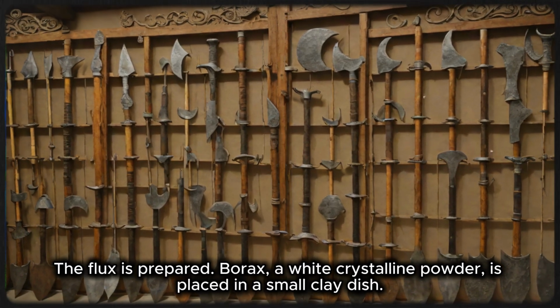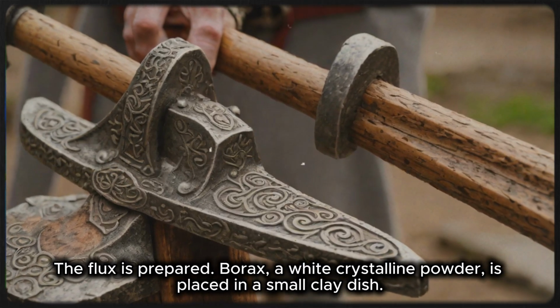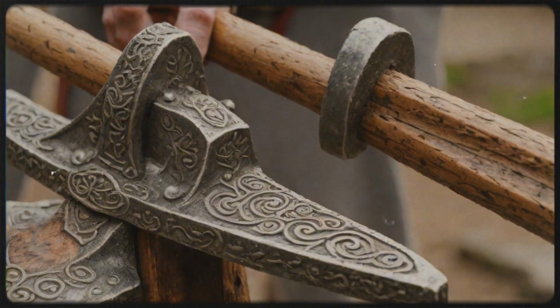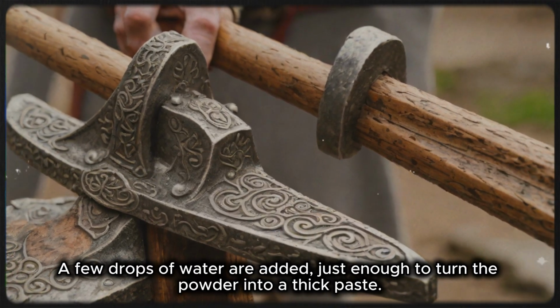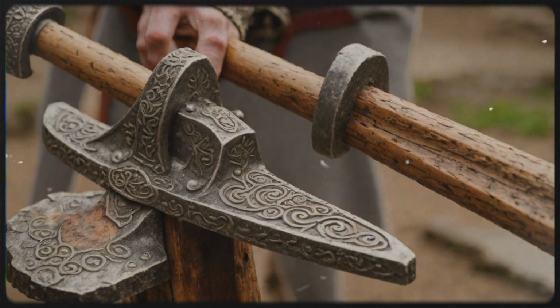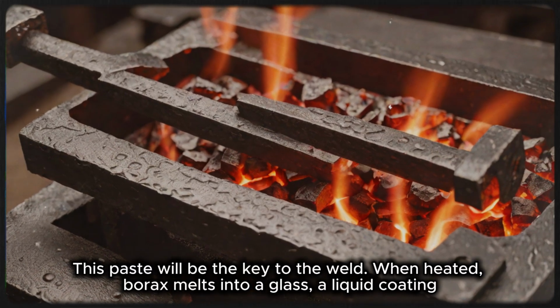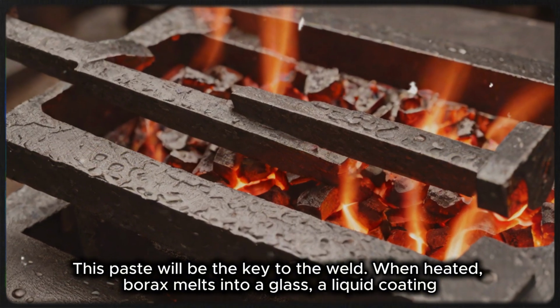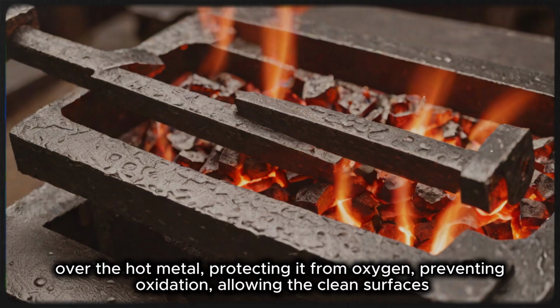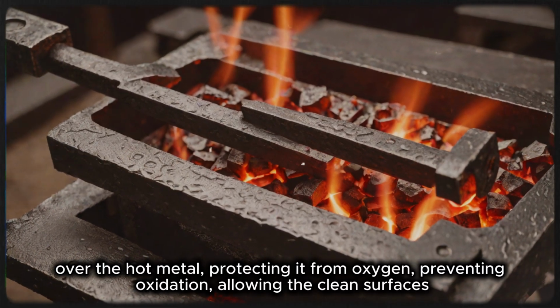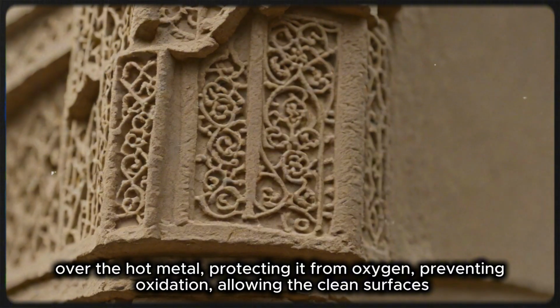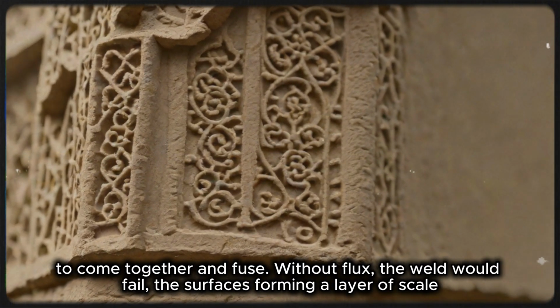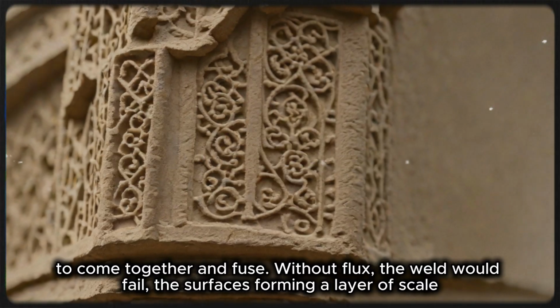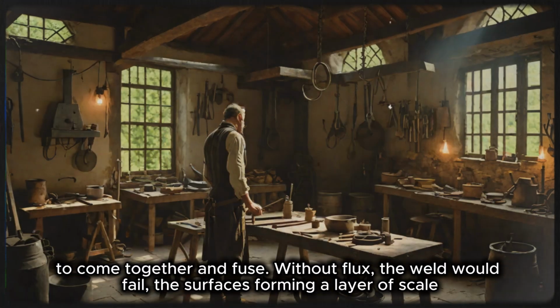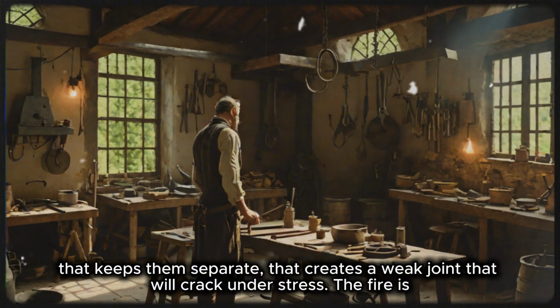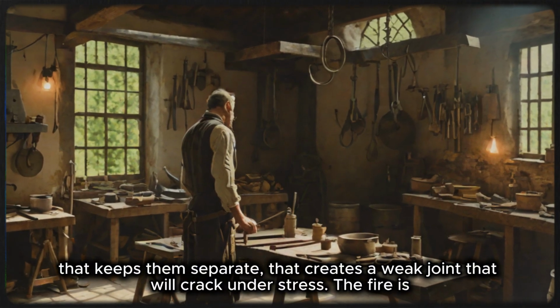The flux is prepared. Borax, a white crystalline powder, is placed in a small clay dish. A few drops of water are added, just enough to turn the powder into a thick paste. This paste will be the key to the weld. When heated, borax melts into a glass, a liquid coating that flows over the hot metal, protecting it from oxygen, preventing oxidation, allowing the clean surfaces to come together and fuse. Without flux, the weld would fail, the surfaces forming a layer of scale that keeps them separate, that creates a weak joint that will crack under stress.